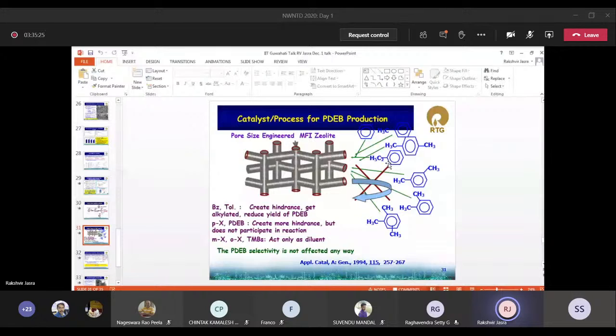Inside, it is producing other isomers, but only the para-diethyl isomer is able to come out, to diffuse, because we have restricted the pores. All other acidity and everything of the zeolite is the same as what people use for this particular zeolite. This is ZSM-5 zeolite. So this really made us have three selectivities.